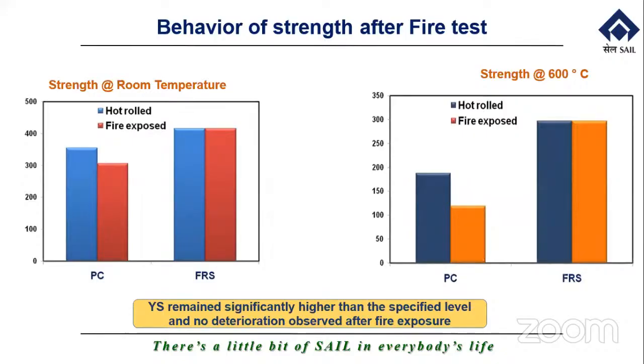When we compare plain carbon steel and fire resistant steel, the hot rolled sections and fire exposed sections, the comparison is given here. The strength parameters for FRS are much higher than plain carbon steel, and at room temperature and at 600 degrees centigrade, both ways we can see FRS performance is much better than any other steel.